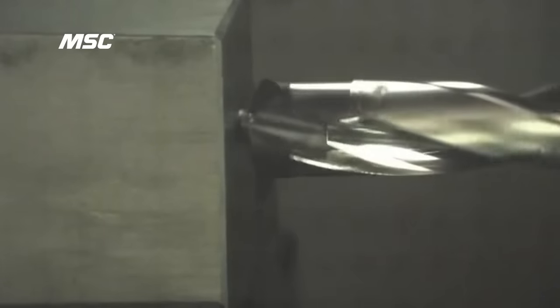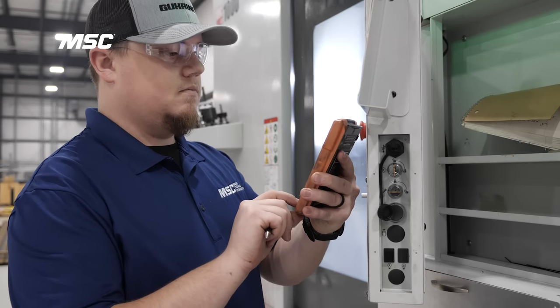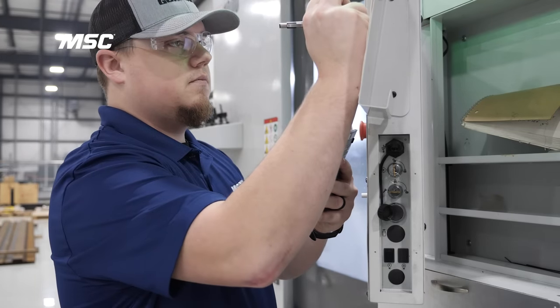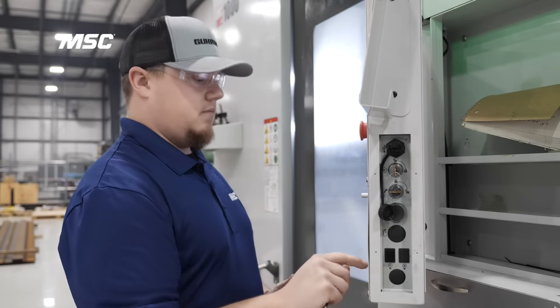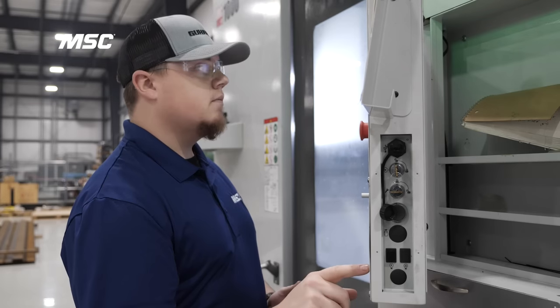Even in the event that you have good coolant flow through the tool, you may unintentionally create a work hardened surface which only makes your job more difficult. As a general recommendation, we advise starting slightly lower than the recommended cutting speed in combination with a fairly aggressive feed rate.